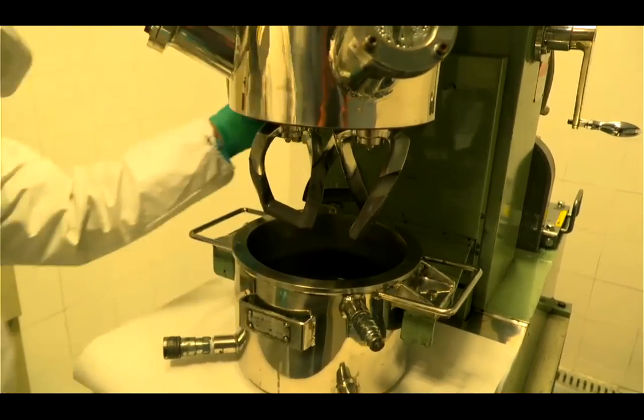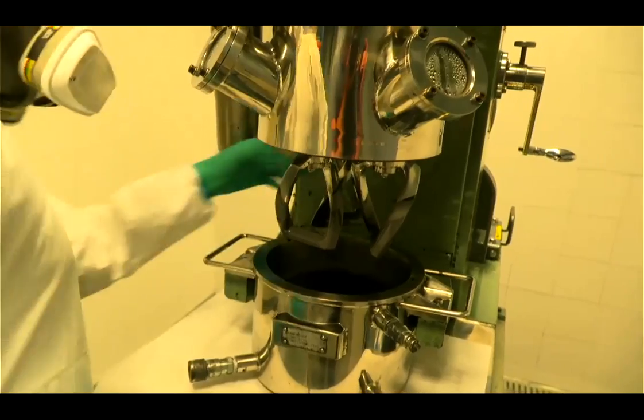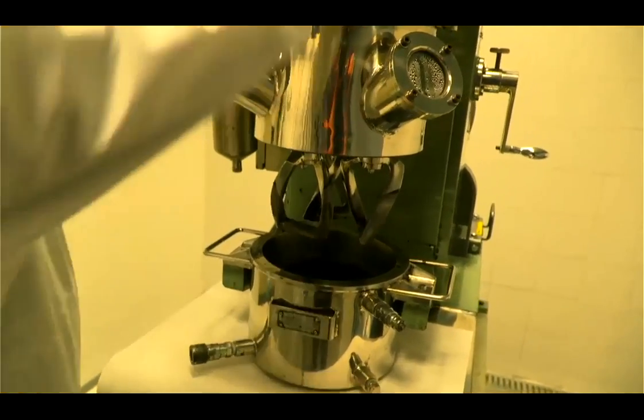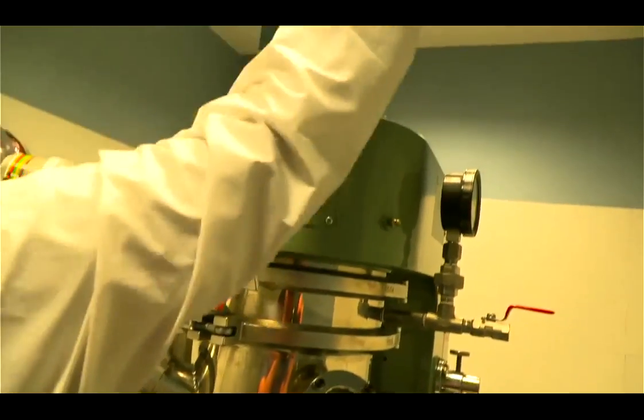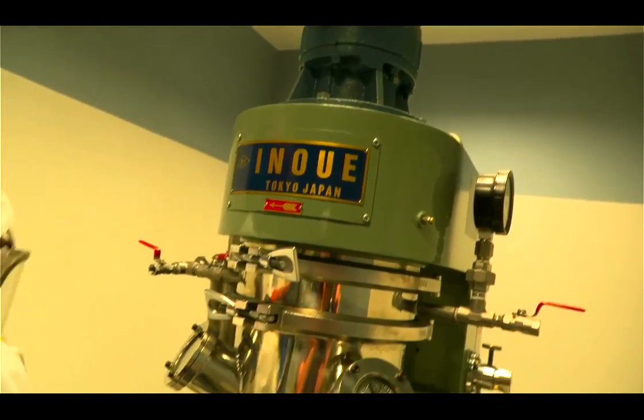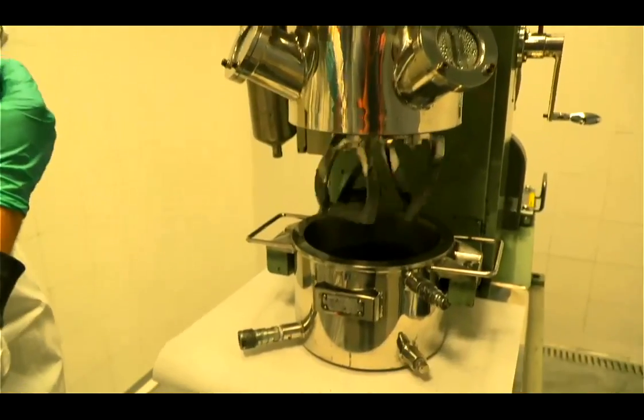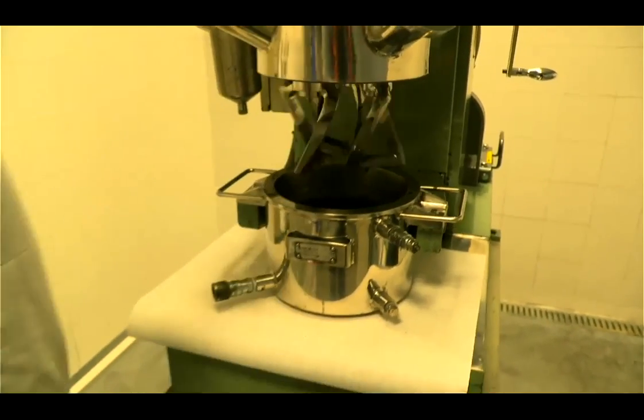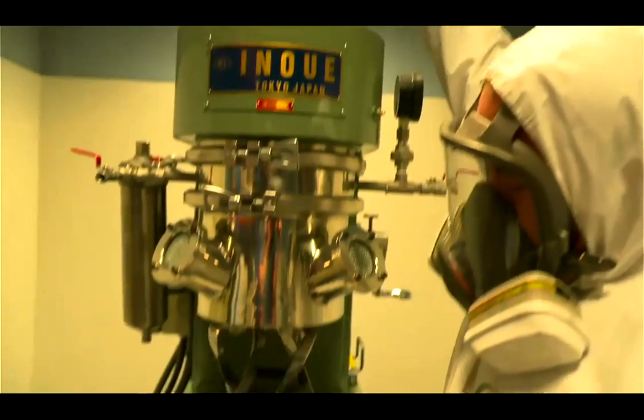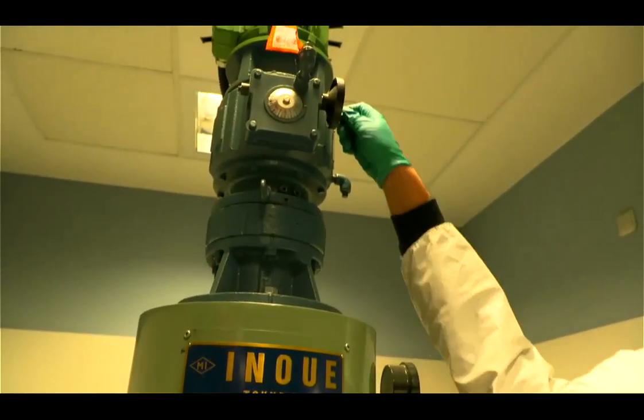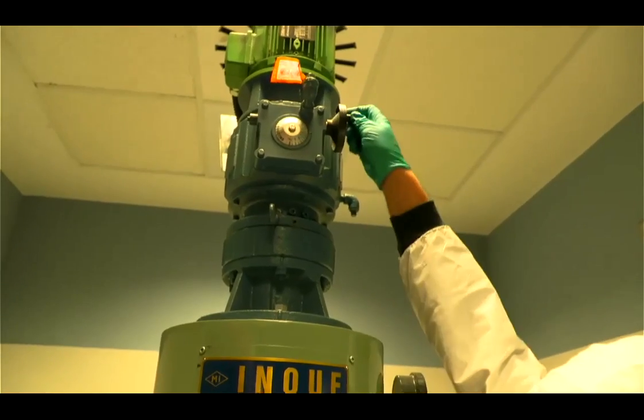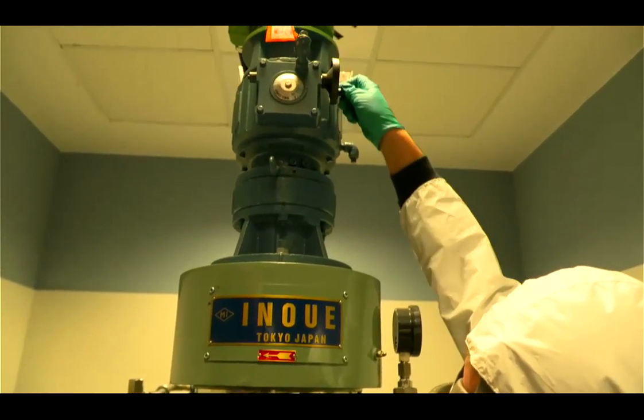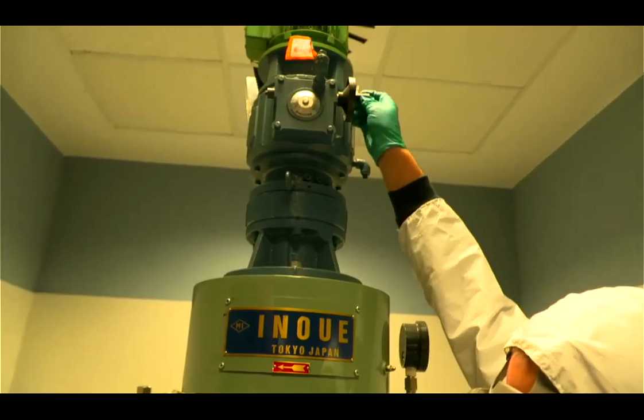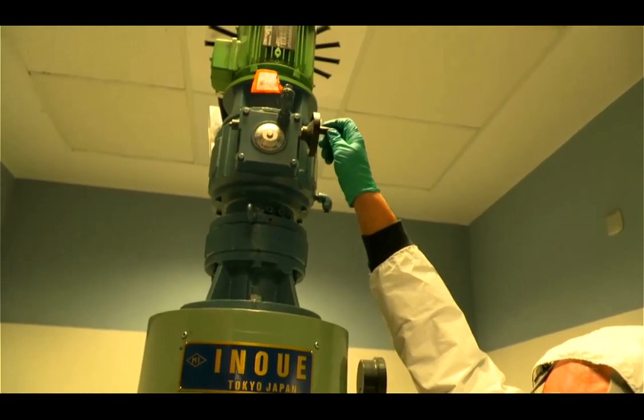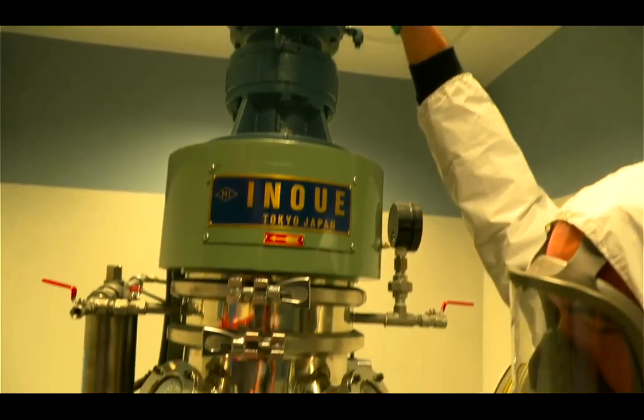If, for example, you are working with a coated LFP, you cannot use high shear devices, because during the preparation of the slurry, you will break the protective layer of the particle. With high shear devices, you also have to be very careful when you apply this high shear. It has to be always before you add the binder, because otherwise you will break the chains of the binder. Okay, but sometimes it is mandatory to do that.